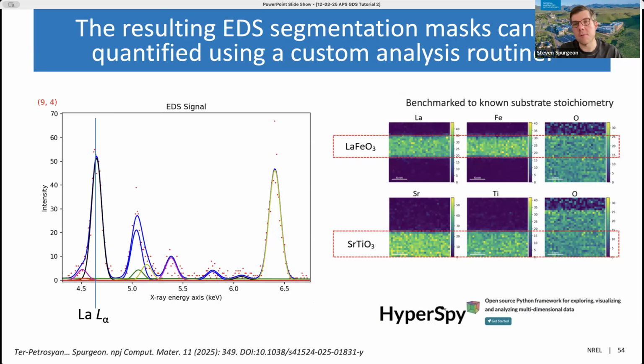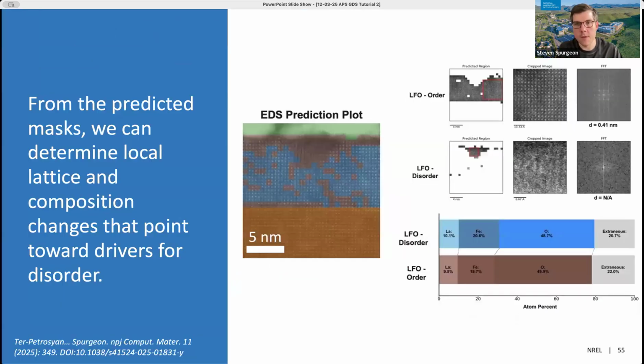So once we've got these predictions from our models, we can go back and say, you've derived these masks, you understand the degree of order in those masks, how can you quantify it in terms of a composition or microstructure? And so we can take those masks and calculate from them compositions within the mask. What distribution of alloying elements are within each of those. And we can do this for arbitrary masks. We can also look at the crystallinity through measuring a Fourier transform of different regions within the material. And what we find, particularly in these systems, is that the initial distribution of alloying elements, having slight defects, for example, in oxygen vacancies, can completely change the response of the material to irradiation in a highly non-uniform way.